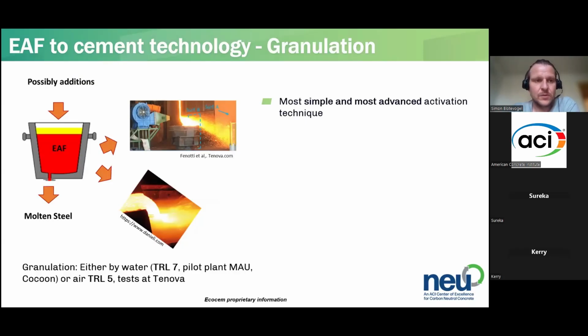The first one is granulation. So what you do is you have your ladle here on the left, or your electric arc furnace, depending on the strategy you're using. You will purge the molten steel, and then you have the slag. What you can do is you can either put it into a slag pit as it's done widely today, or you granulate it. There's different types of granulation that are well known, either air granulation or water granulation, to produce a more amorphous material. This is clearly the most simple and the most advanced technique because it's just really letting things flow into a granulator.